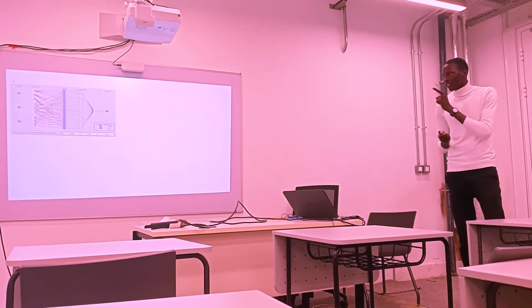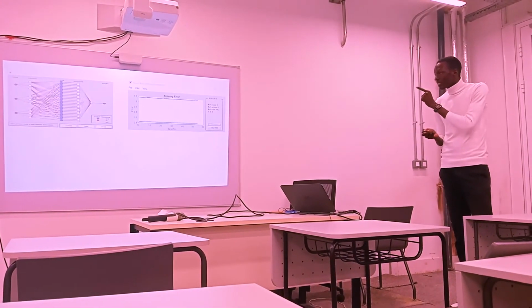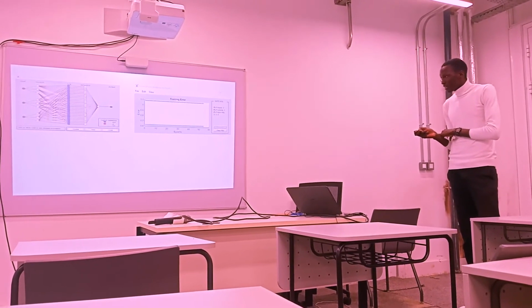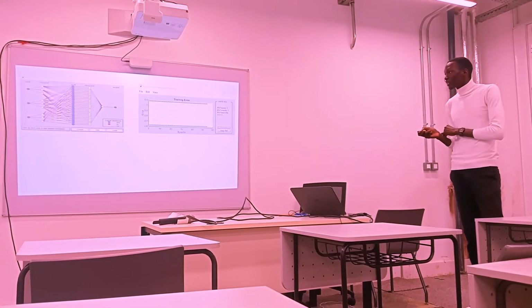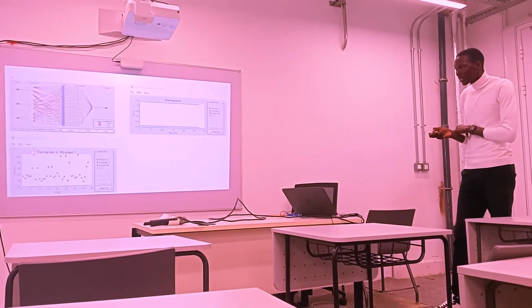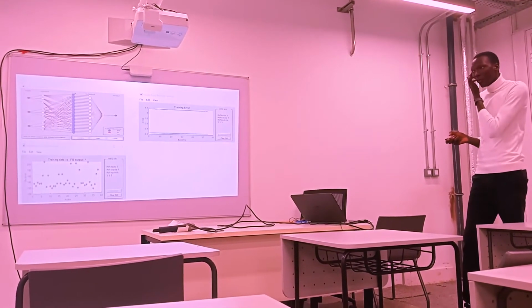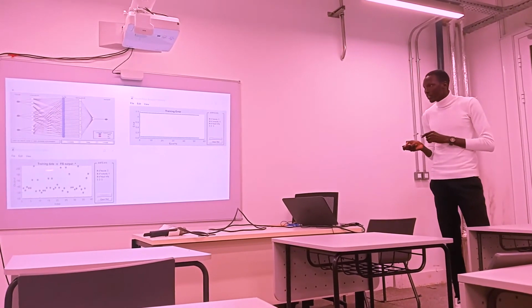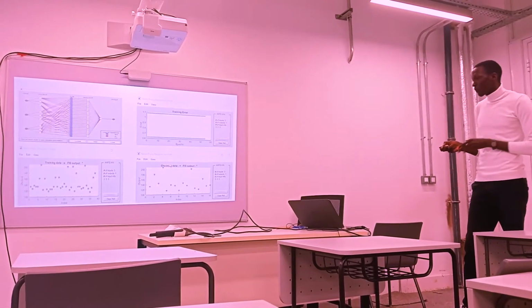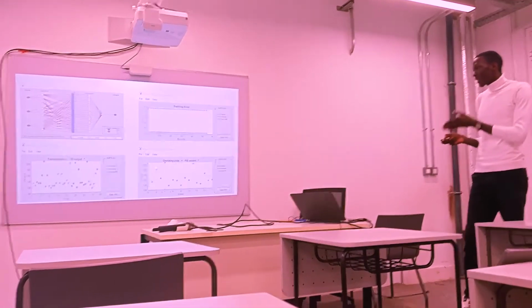And then this is the structure of the ANFIS for width. Then this is the training error, which did not exceed 1.1. And then this is the plot of the training data against the predicted values under the same condition. I said we used 70% of the data for training, and then 30% for testing. And this is the plot of the testing data with the predicted values.